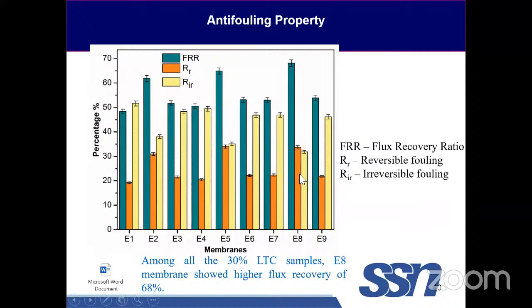This is the drop. This is the initial pure water flux. After blockage with the protein, it has dropped to here. After washing the protein, again it has recovered higher, quite similar to that. In other cases, the recovery is quite less. And then we checked the adsorption of dye over the membrane.